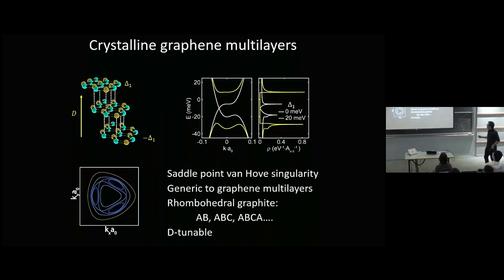Okay, and the ones we're going to be most interested in this talk happen for hole doping, due to the details of this band structure. There, the Van Hove singularities are much closer to a finite density saddle point where you have pockets around each K point that start to touch at some finite momentum, and you get a divergent density of states.